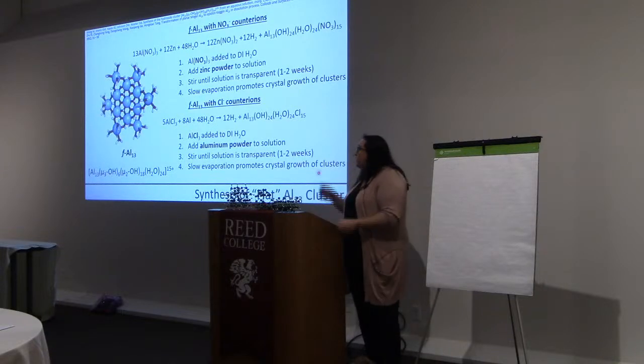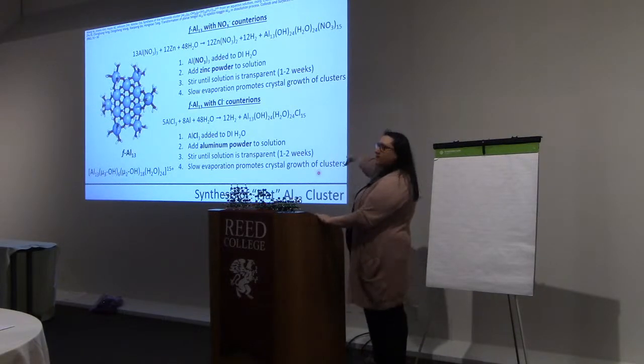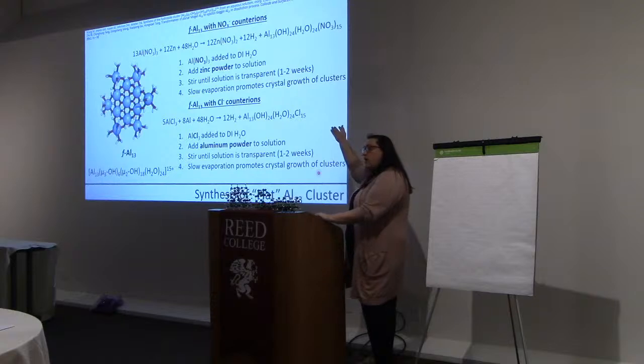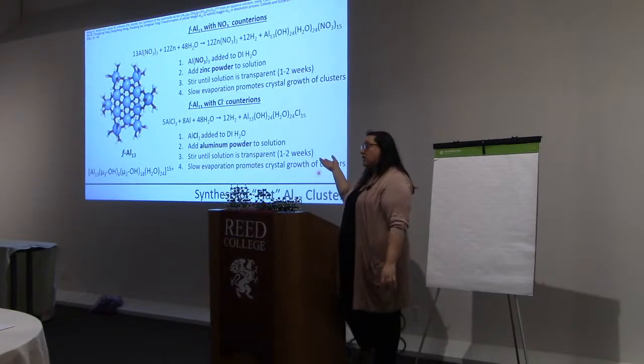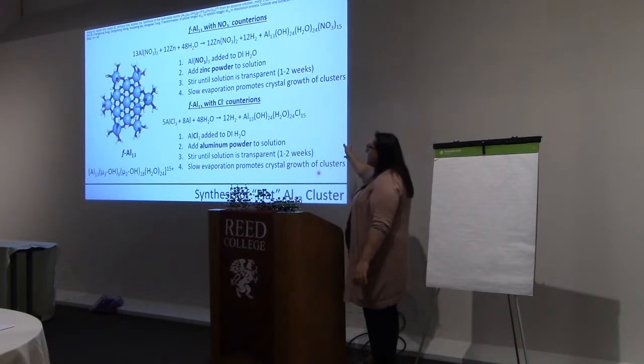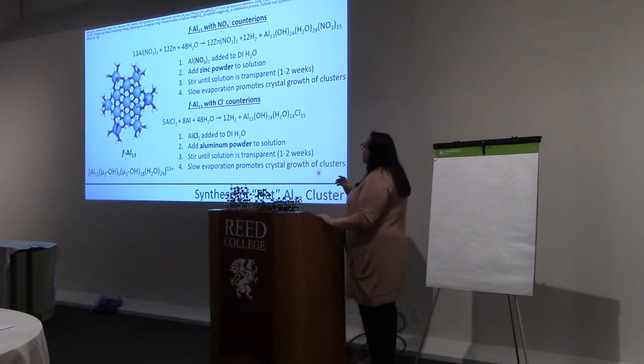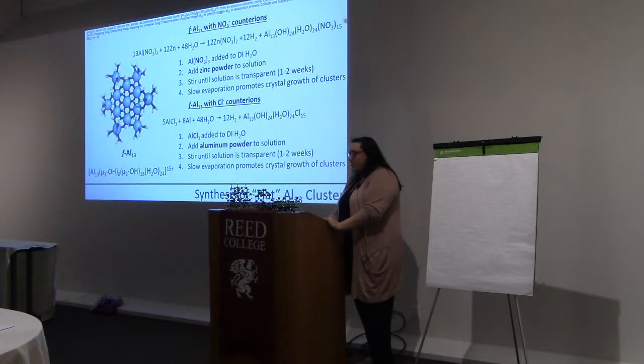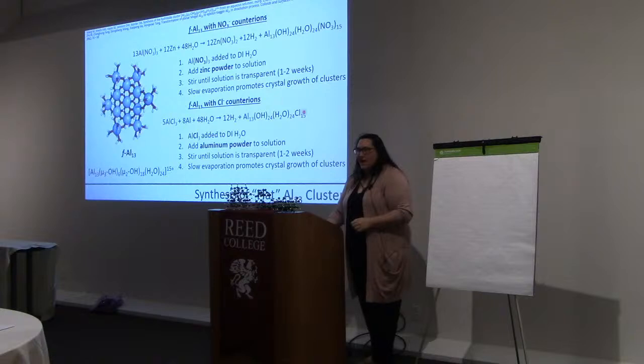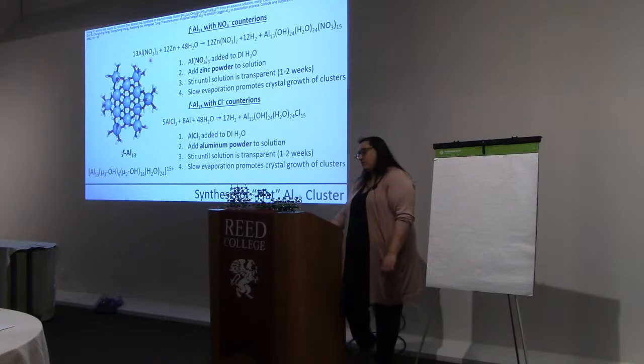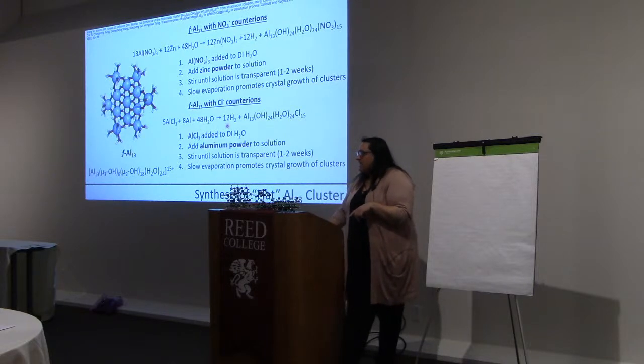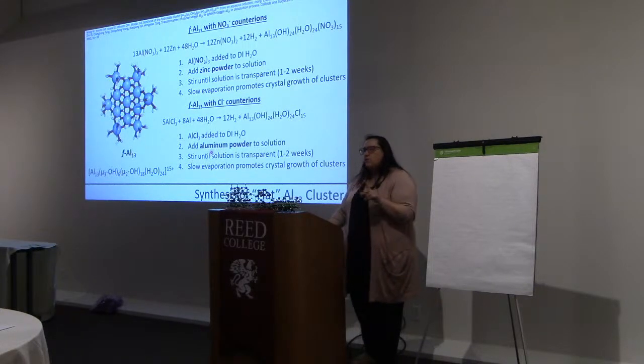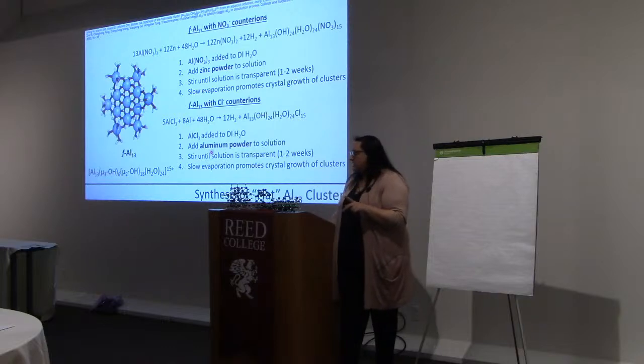So here I found in the literature 2 different syntheses. One of these my colleagues were doing at U of O while I was working on the gallium clusters, and the other one is just from the literature. And so they're very similar, but one of them is creating the cluster with nitrate counterions, and the other is creating the cluster with chloride counterions, mainly from our starting material, right? We start with aluminum nitrate or aluminum chloride. The other difference in the syntheses is that they're using zinc versus aluminum powder to reduce the solution.